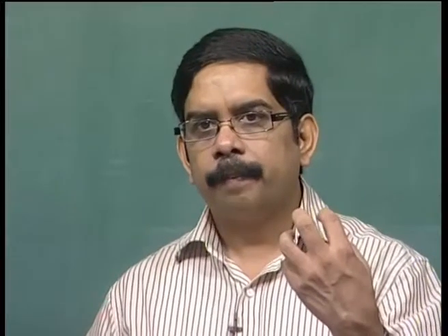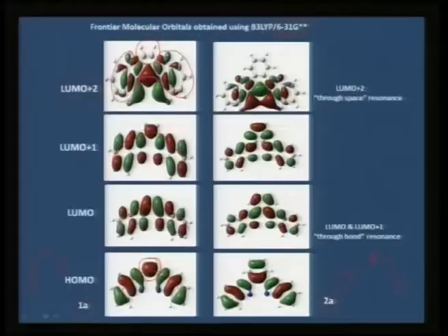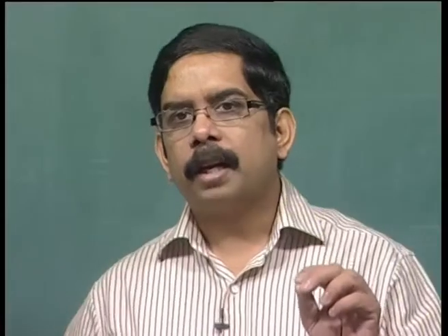Why? Because sulfur atoms are much bigger and they carry lone pair of electrons. Therefore, the charge resonance is not only through the bond but also through the space. So, you have a through space resonance in the case of sulfur atoms, which is peculiarly absent in the case of imidazole or oxazole. You would not see the same picture if you look at oxazole or imidazole compounds.